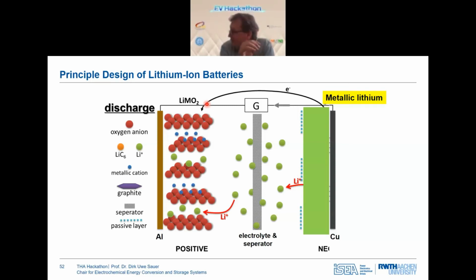And the highest energy density can be achieved, obviously, if we would have a pure metallic lithium electrode. But this is something which is not working with today's liquid electrolytes, because the liquid electrolytes used and the metallic lithium will have a strong and ongoing electrochemical reaction, which will age the battery in very short time dramatically.